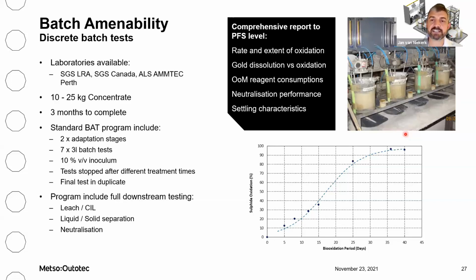It is really just a set of standard laboratory reactors that is stopped after different reaction times to give you the correlation of sulphide oxidation with bioxidation period. Typical batch bioxidation periods are much longer than the corresponding continuous retention time required on a commercial plant due to the mechanism of a batch test.